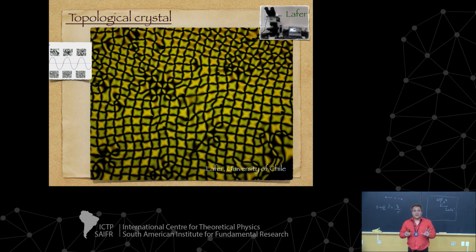The only problem of the liquid crystal is that when the temperature is very low, in this kind of experiment minus 10 or 20 degrees Celsius, after that it becomes a crystal. Initially, it was said that liquid crystal has a vector field, so we expect to observe a Kosterlitz-Thouless transition. But for this material, the problem is that the prediction of the theory needs low temperature to observe this kind of thermodynamic transition, and at low temperature this material cannot exist. So this kind of transition is not possible to observe in this material, because all the liquid crystals that we know work at a good temperature, even a high temperature.